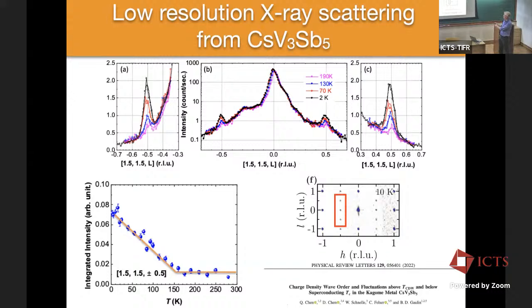In fact, the scattering at 0 is about 100 times stronger than the scattering that I'm going to focus on. Most of this scattering is temperature independent, below 300 Kelvin, okay? And it corresponds to some fluctuation that has a doubling of the unit cell within the Kagome plane, because it's at these 1.5, 1.5 indices in reciprocal space. So most of this scattering is temperature independent, but when you come to L equals +1/2 and -1/2, you get some more Bragg-like feature that actually is temperature dependent, and this is the signature from the charge density wave, which everybody else is seeing, although, as I'll show you, it's somewhat different.